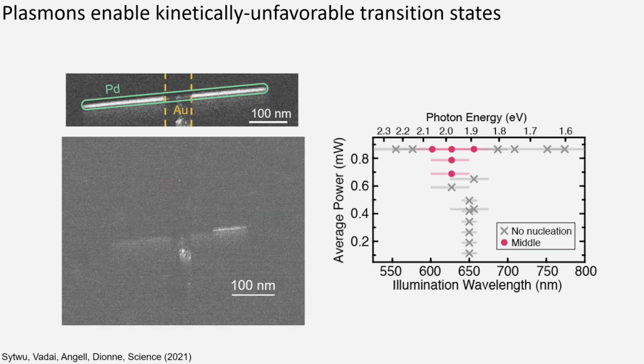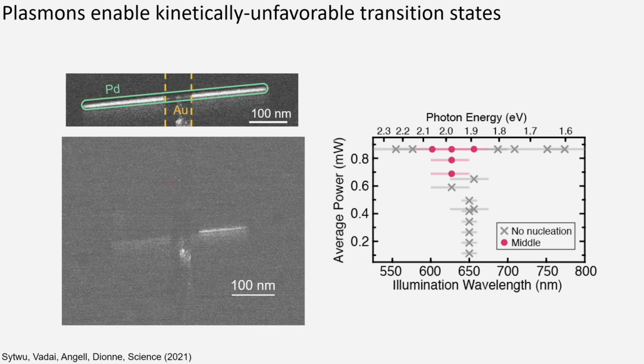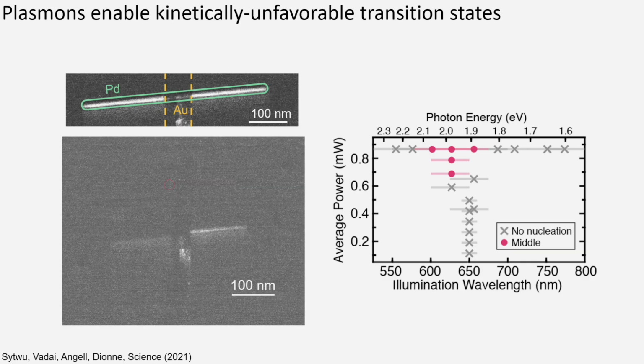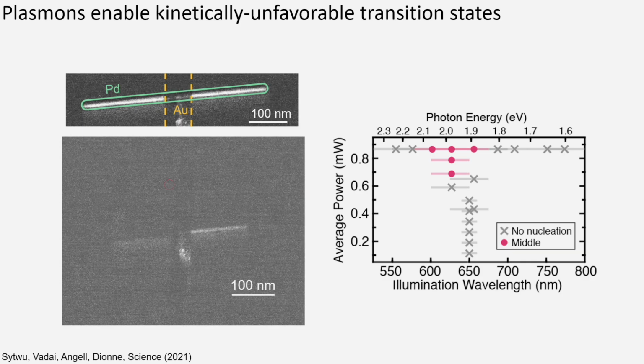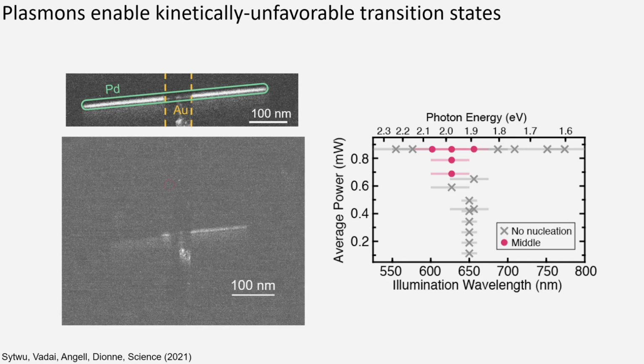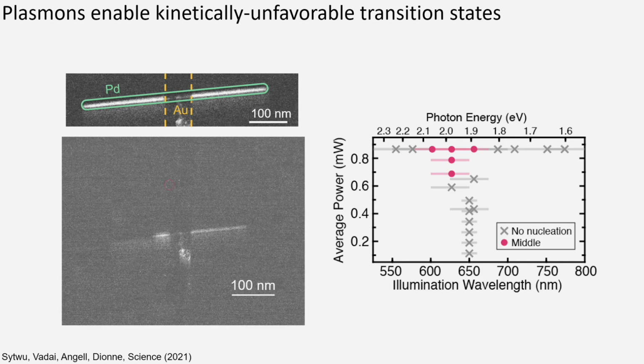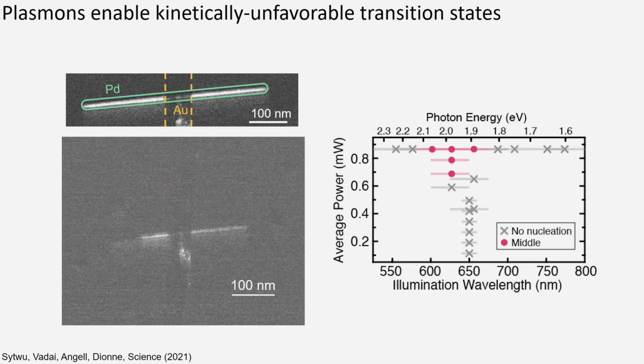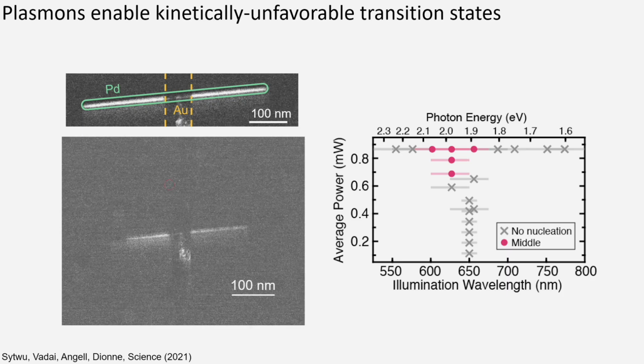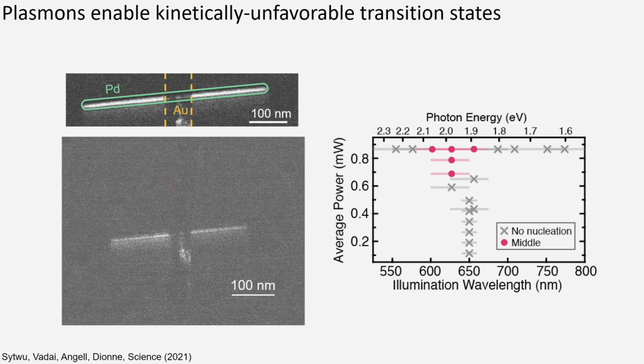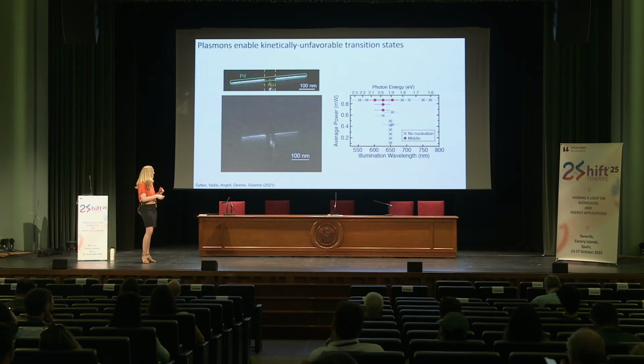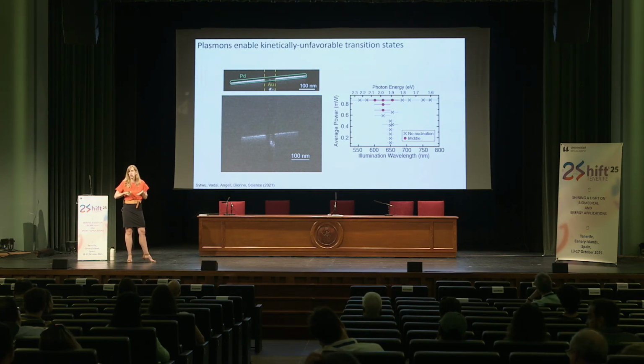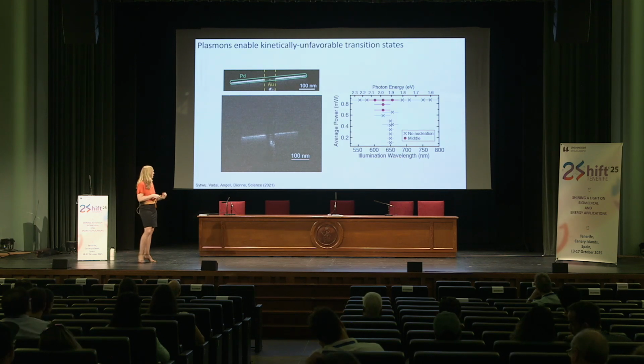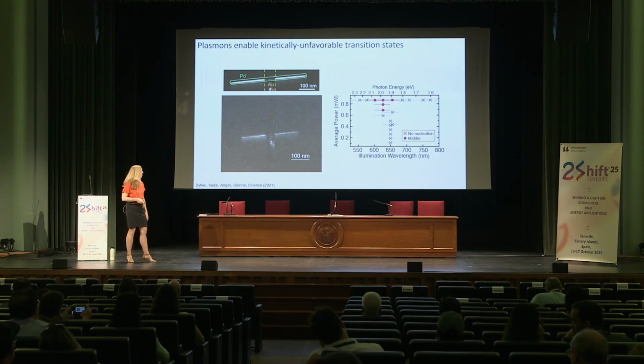So you can do this over and over again, and basically you can nucleate where hydrogen is entering the rod and where hydrogen is leaving the rod simply by using the light to trigger the reaction. So with the light on, we basically trigger the reaction at that electromagnetic hotspot. With the light off, we only have hydrogen entering from the tips. And here we did this as a function of the illumination wavelengths. So you can see only when we're illuminating right around 600 nanometers do we actually get this effect. So you have to be at that plasmon resonance of the nanoparticles. Otherwise, you basically get no nucleation regardless of what wavelength or what power you're illuminating with.